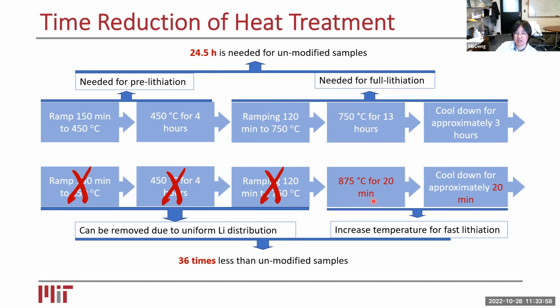However, in our case, since our particle is so robust, we can ramp the temperature up to 875 Celsius, and we do not need to have this gradual ramping, and we do not need to cool down slowly. We just take it out and let it cool down in air. So totally it's only 20 minutes. So we have a significant decrease of annealing time, in addition to the 50% of time cut happening during the synthesis of the particles.